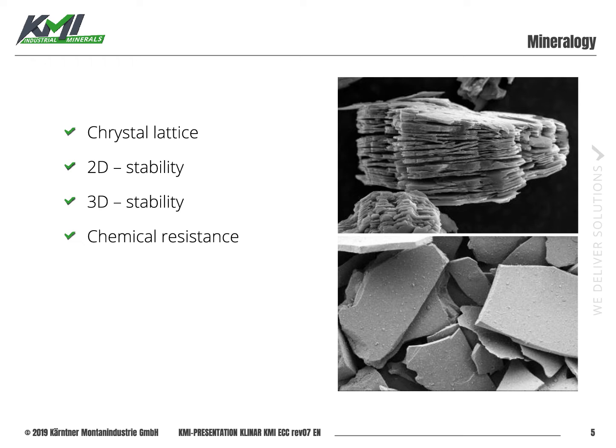So if you have, let's say, an attack of a salt solution in a coating, the salt solution can penetrate the space in between the layers and can crack the particle. When you look at the micaceous iron oxide, this is the picture on the bottom of the right hand side. It's a three-dimensional stable particle, so there's no space to penetrate, and it's a very chemically resistant mineral.